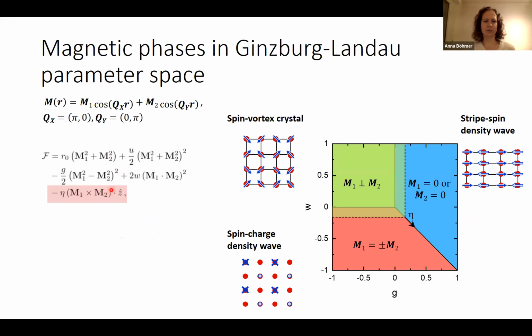I add another term with this field eta from the symmetry, different symmetry in the 1144 structure. So in the 1144 structure with a finite eta, this spin vortex crystal phase is enlarged because of the coupling. And that's where this relation comes from. And we're wondering what's the effect on the nematic fluctuations of this spin vortex crystal structure and of this additional